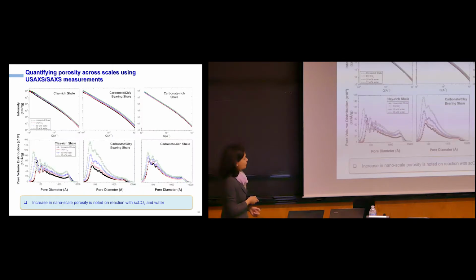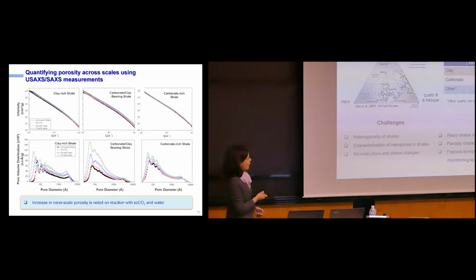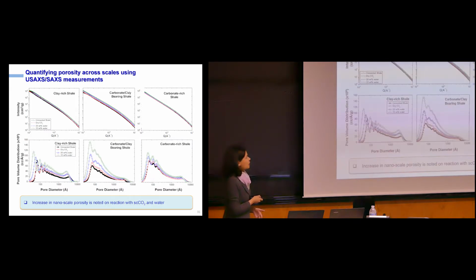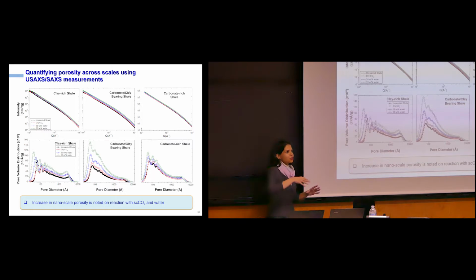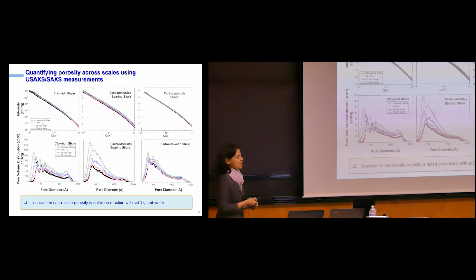Turns out that when you react these materials with just dry CO2, not a lot happens. But when you react these materials with a mixture of CO2 and water, a lot of changes happen to the structures and the microstructures of these materials. So to non-invasively probe what is happening to the pore structures of these materials, we did some ultra-small and small-angle X-ray scattering measurements. As an alternative to BET measurements, where you're using gas absorption to probe some of the changes in the pore structures of these materials, we're actually using non-invasive X-ray scattering methods.